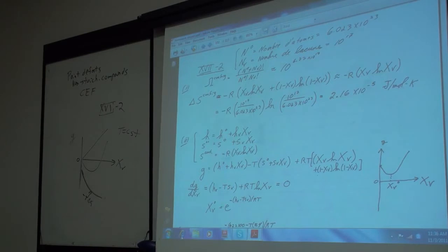You cannot eliminate the vacancies because the vacancies decrease the Gibbs energy of the system up to a certain point, and then increase it. So you might say that a metal at equilibrium has a certain equilibrium number of vacancies in it. Unless you're at 0 Kelvin, every pure metal has an equilibrium number of vacancies.